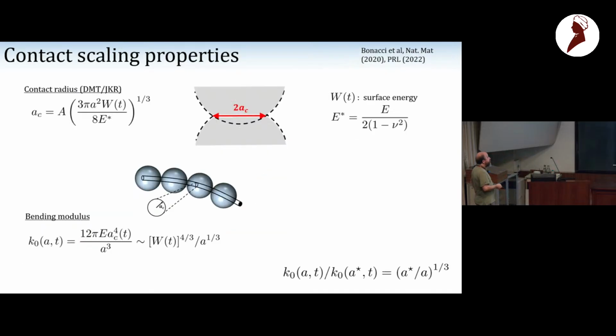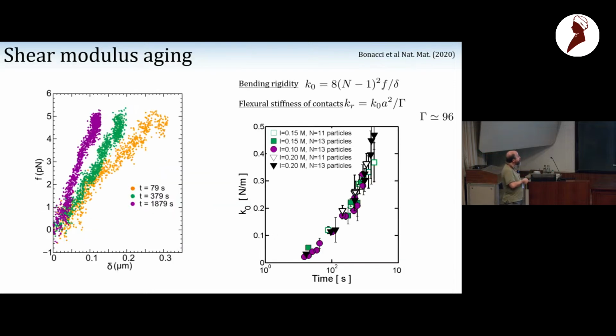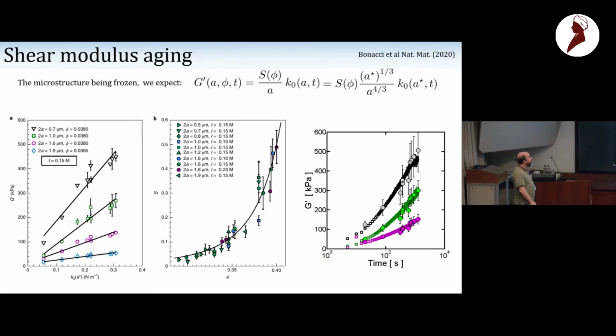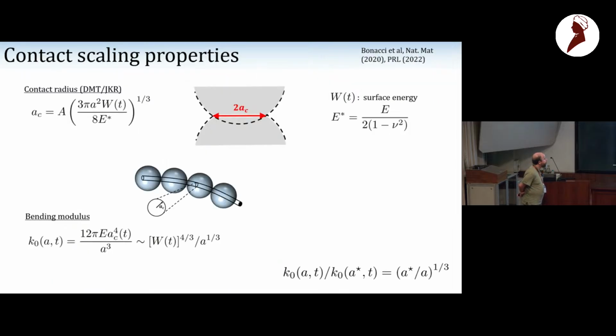So the only reason why we do that is because we cannot measure this on many particle sizes. We can measure that on one particle size. Yeah. Just to clarify this point, the picture you have is that when you have these things stuck, at any point in the interface, you have elastic response, so you're just scaling with the area. That's what the contact theory tells you, that indeed the elastic modulus scales as a function of the area. Yes.